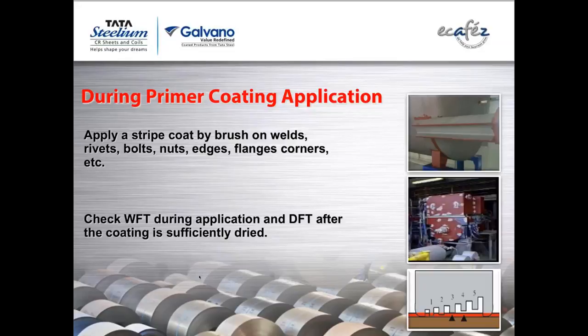Now, when it comes to final DFT checking, we realize that it is only 150 in certain areas. It's going way below the expected by the customer. So we make it up by applying the final PU coat. Now this particular thing, one thing is we are not giving the enough thicknesses to earlier coats which are going to give you protection. And we are going to increase the DFT of the final coat, which is not going to give you that much of corrosion resistance. And secondly, these top coats are also more expensive. So we end up spending more money than the primers. And ultimate corrosion resistance is not going to come. So using this WFT is also very important.